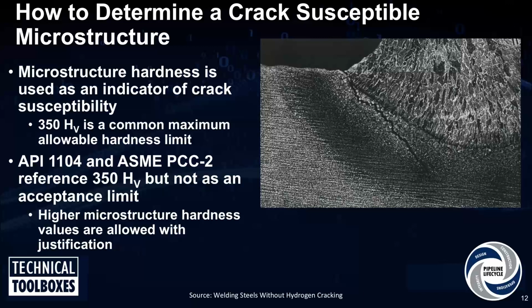Now, this 350 number is in a lot of the in-service welding qualification codes. So it'll say in API 1104 that if your weld hardness is over 350 Vickers, you need to evaluate your weld for hydrogen cracking. But it's not an acceptance criteria. It's not a go no go acceptance criteria for weld microstructure. It's, hey, if you're over 350, you might want to be worried about cracking.